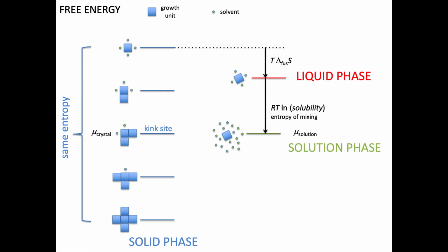Now when we start our crystallization, we start from a supersaturated solution, so we are not at the equilibrium level here, but we are at some higher energy here, whereby we add nutrient at a higher free energy. If that was a framework material like a zeolite, that could be the gel phase. And the free energy above the equilibrium state will be RT ln of the supersaturation. So this is the energy level diagram which we're using in the